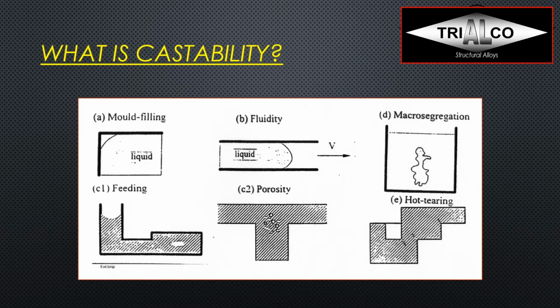So now let's have a look at castability. What is that? Well, we said it before. First of all, it has to be mold filling. I need to be able to fill the cavity in the mold completely. So this is when we are completely liquid, and I need fluidity. Fluidity can mean flow length per wall thickness of the casting, for example. Once the cavity is filled, then I need to be able to feed. I need to be feeding the shrinkage and compensate for that shrinkage. If I can't do that properly, I will see porosity. We call this shrinkage porosity, and we can see it up at the top right. Then I can get macro segregation. And if I have a hot short alloy and I can't feed it anymore and it shrinks and is restrained in the mold, I can get what we call hot tearing.